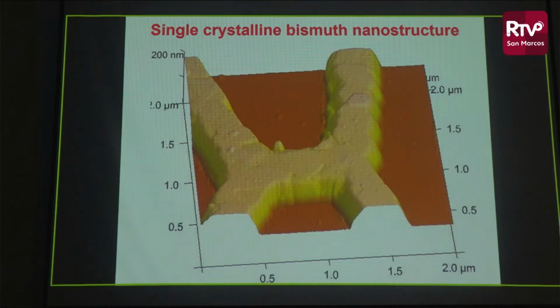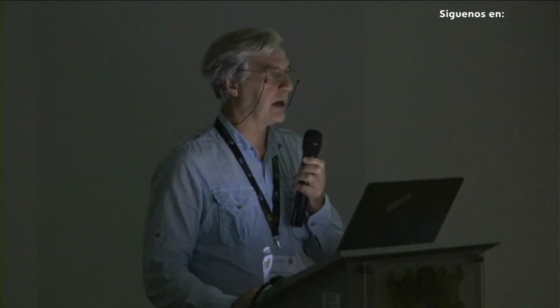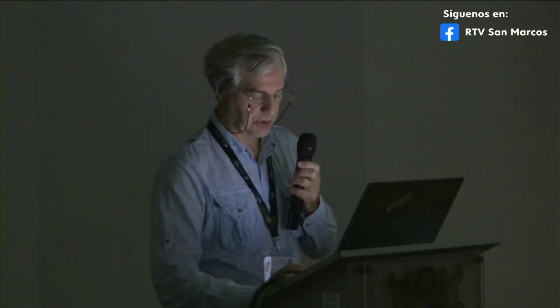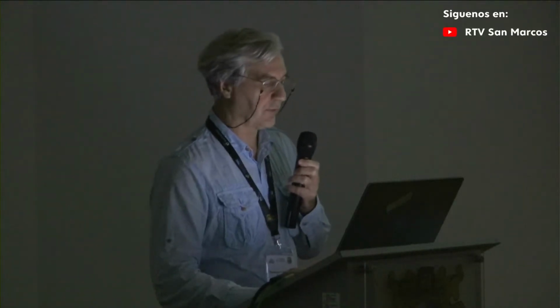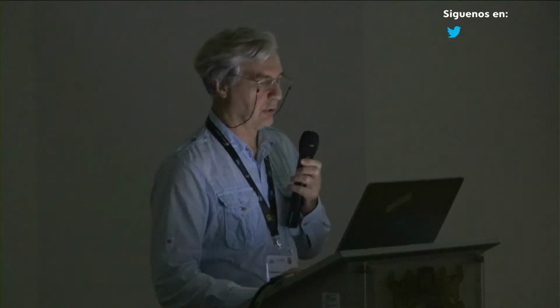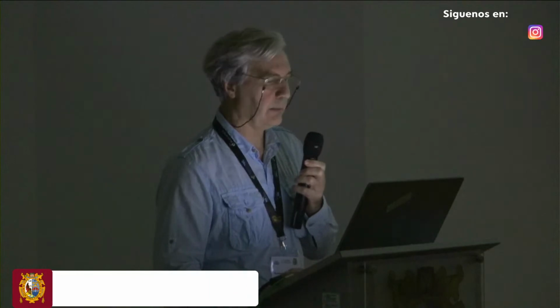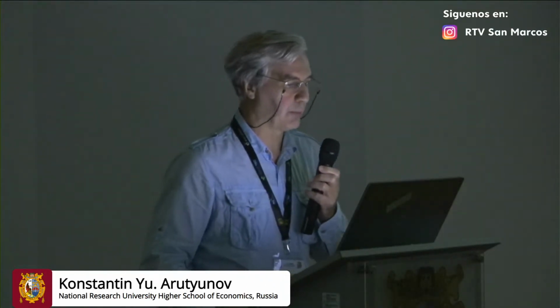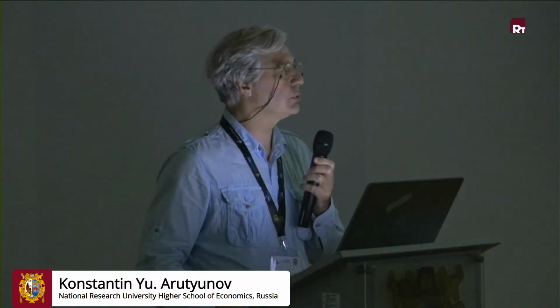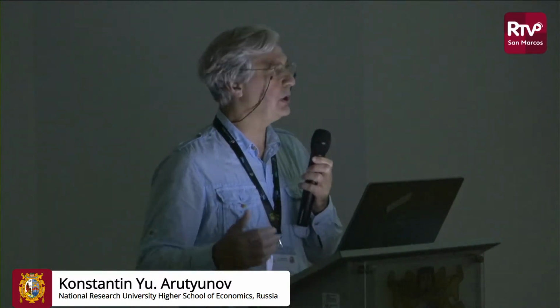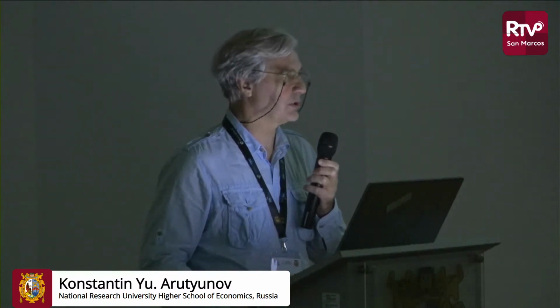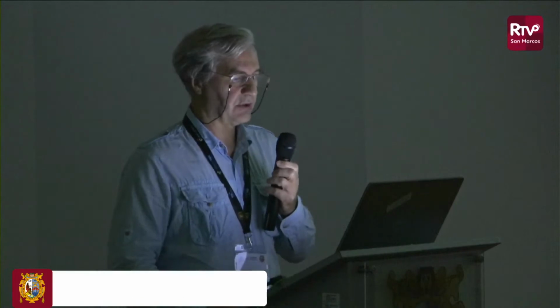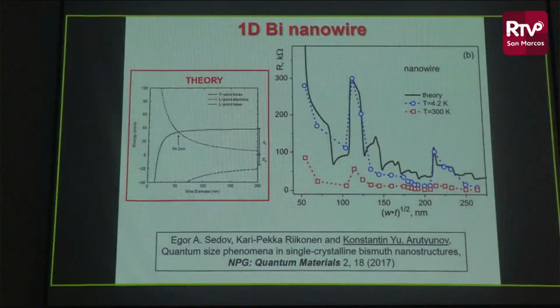But one should fabricate a single crystalline structure. And we spent about 2 years to fabricate single crystalline bismuth nanostructure on the surface of mica. Mica is necessary to make it really crystalline. So that was our working nanostructure, and then we measured the resistance of the central part, reducing the cross-section of the nanowire by our proprietary ion milling method. Theory predicts that when the system approaches the level of about 50 nanometers, it should turn from normal metal to insulator. But in between, each time the quantized level crosses the Fermi level, we should have a singularity of resistivity. The right plot shows the experimental data, let's say at 4.2 Kelvin, the blue dots, which more or less nicely follow the prediction of the theory, the dark black line here.